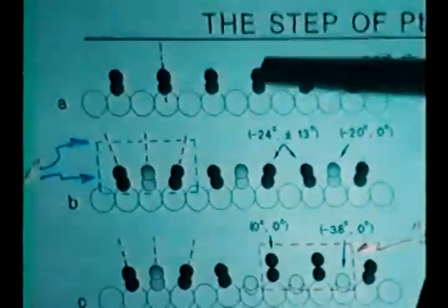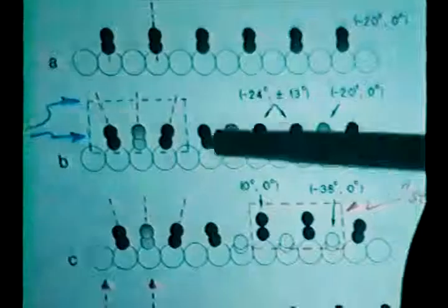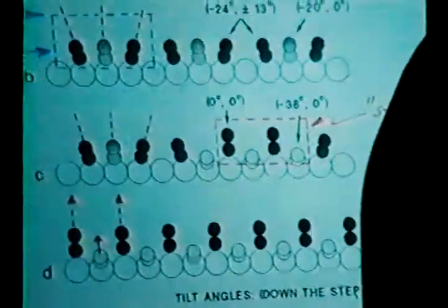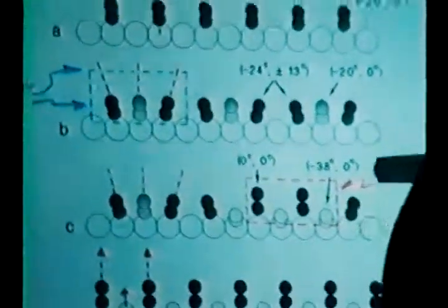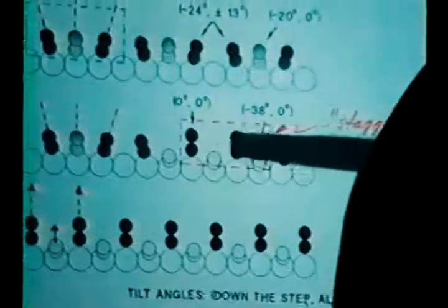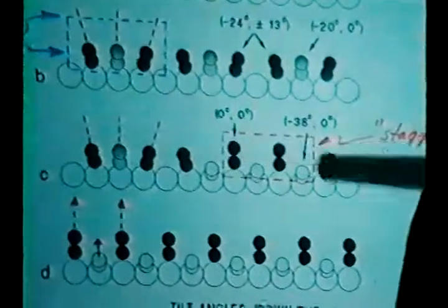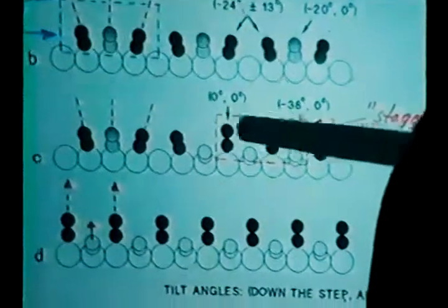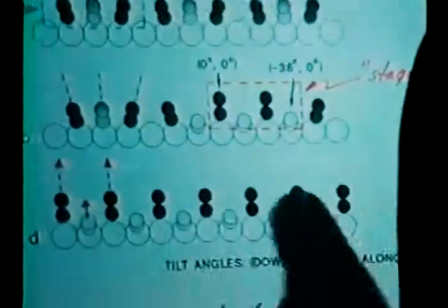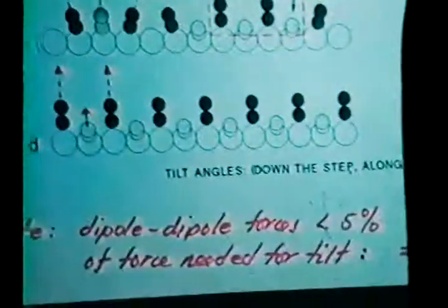As we continue to fill up the holes in this one-dimensional array of molecules on the surface, to relieve the strain that exists from the repulsion of these molecules, the molecules do the only thing they can do when they get crowded together, is to tilt backwards and forwards in the high coverage conditions where there are no empty sites left on the surface. So you get a 38-degree tilting in these staggered structures as you fill in those empty defect sites on the step surface. And finally, you can fill the steps up completely with the forward and backward filled with CO molecules.